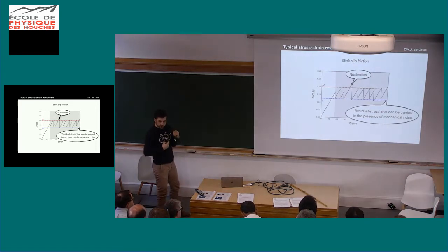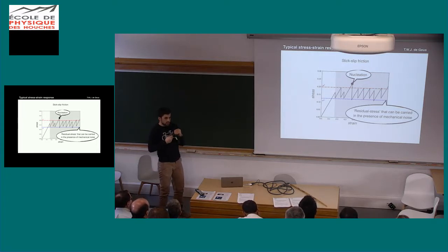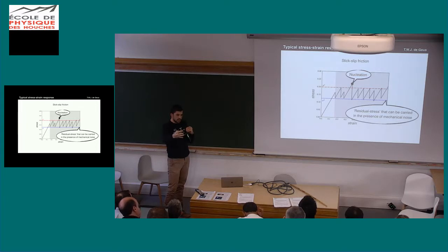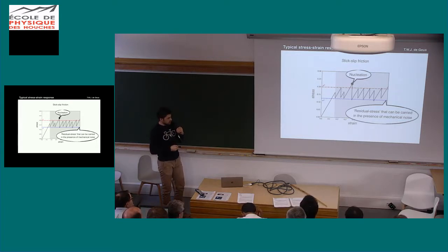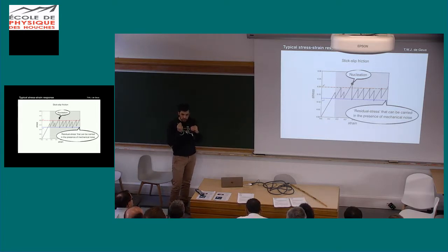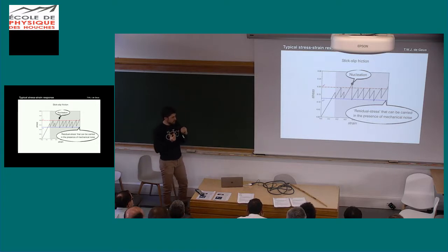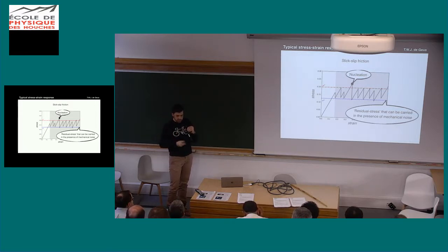We had this clear rupture front, but maybe not. So what happened after this nucleation of this big event, the stress dropped, the entire system was destabilized, and you noticed maybe that blocks kept yielding over and over again until the system stops, and it stops at some residual stress that I will call sigma bottom. And the residual stress is actually a critical stress for our system, and that is the stress that the system can carry in the presence of inertia. So in the presence of all these elastic waves, the system will stop at the sigma bottom.